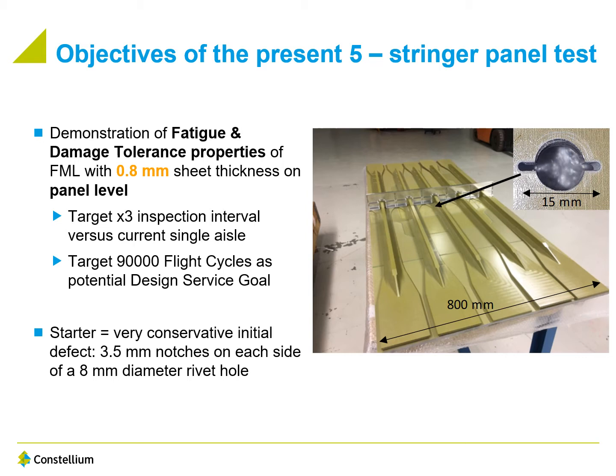Now we come to the objective of the test that we have performed. For making a lower wing, we want, for cost reasons, to have a thicker metal sheet compared to what we have in the fuselage. So it makes sense to make a test that would validate this increase in thickness. But still, we want to have the attributes of the FML, that is a very large inspection interval possible. So we target a factor 3 versus a current inspection interval. And also we want to target a very high design service goal, that is the fatigue life of the panel.